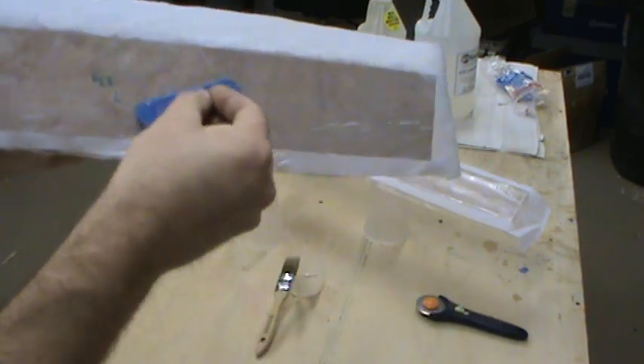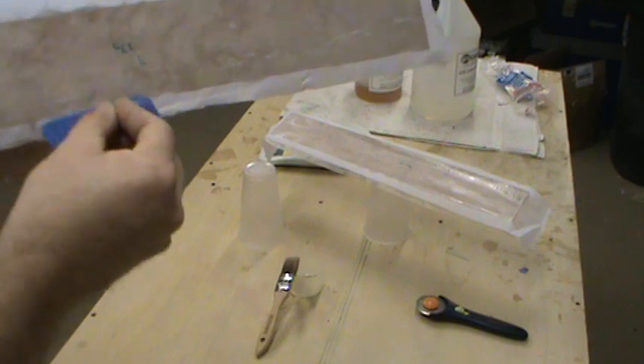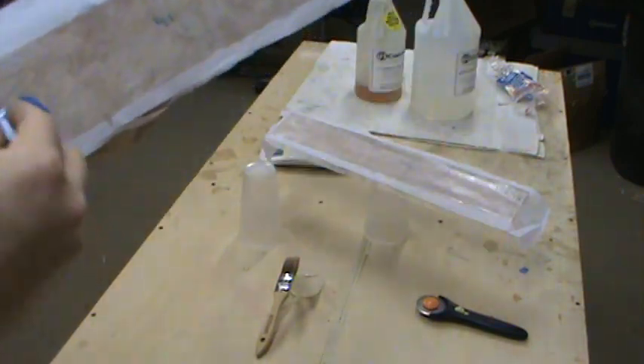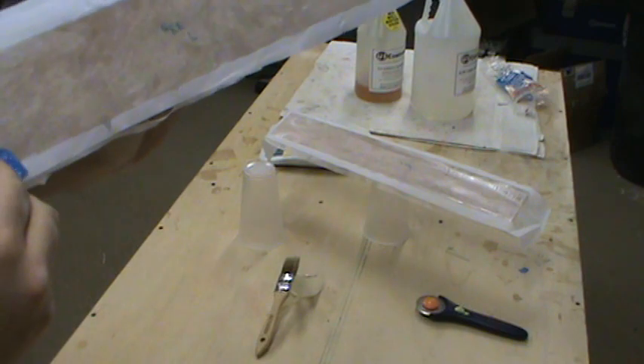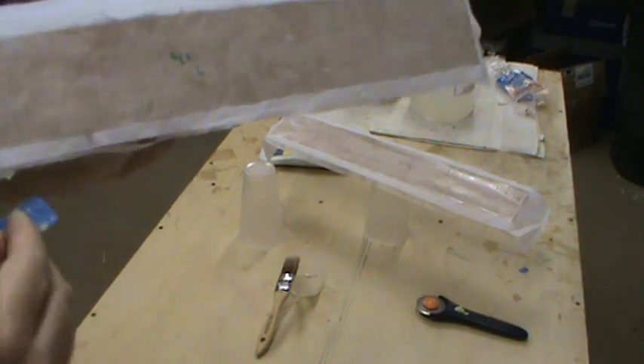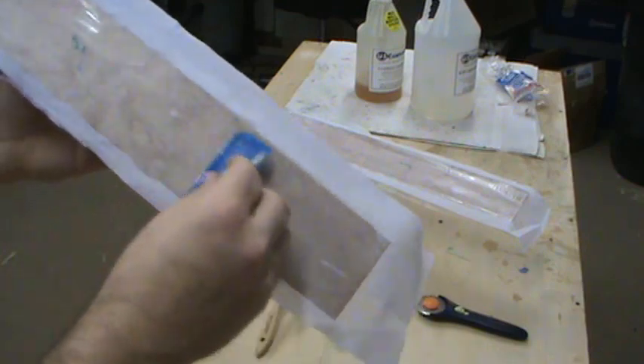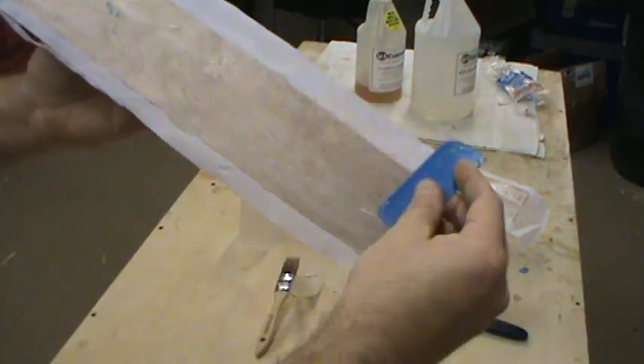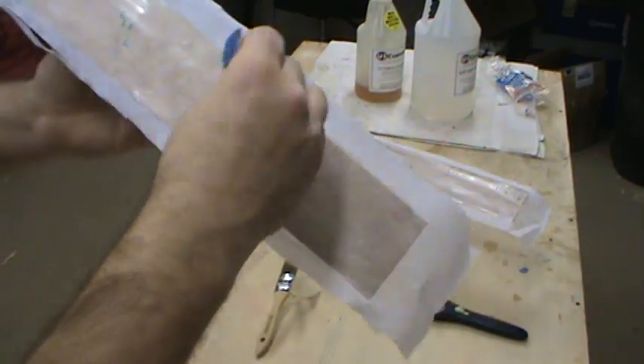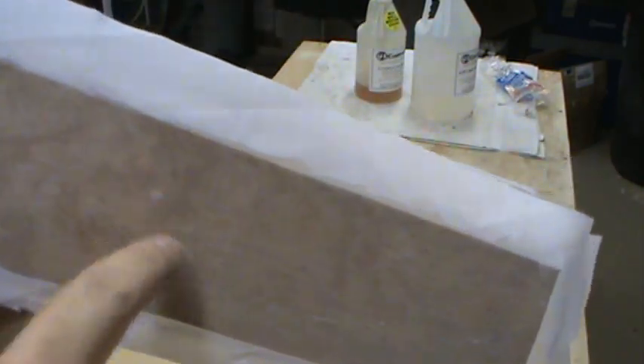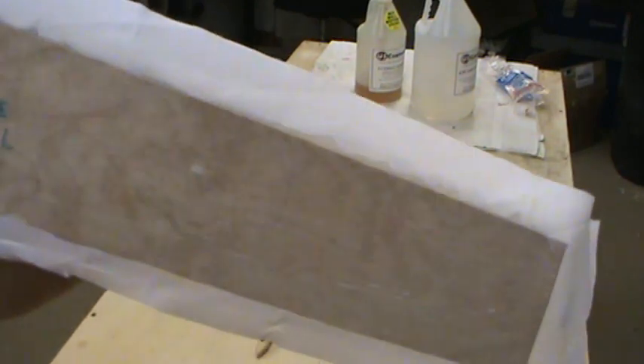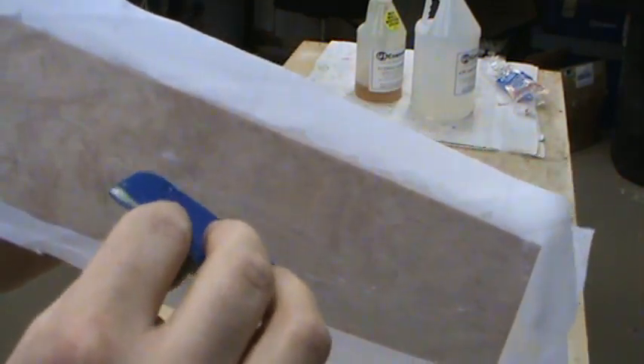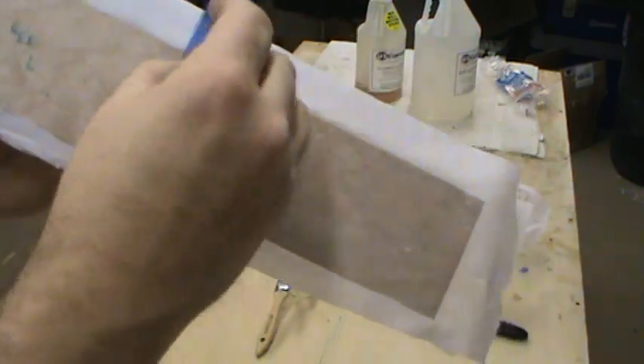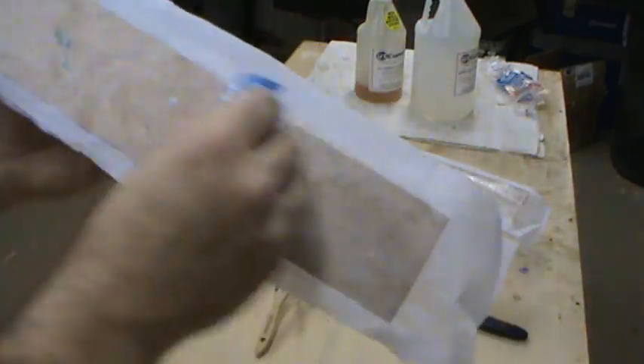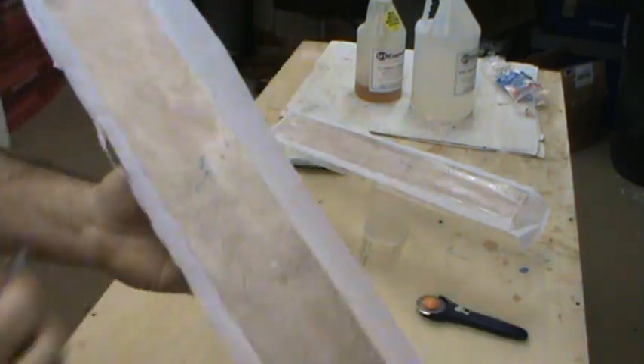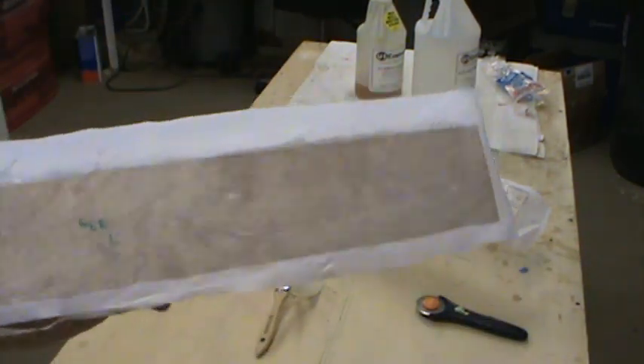This peel ply also helps you find areas where the fiberglass cloth up under it has folds in the fibers, or where there wasn't quite enough resin, so the glass in that particular area was a little starved, or there might be a little piece of trash under the cloth, not letting it lay completely flat. Like right here, you can see there's a little bit of a bump. That's just a piece of trash on the part, and you'll end up sanding through the cloth there. Not much we can do about it right now, but we'll get to that issue when we get to the painting stage.